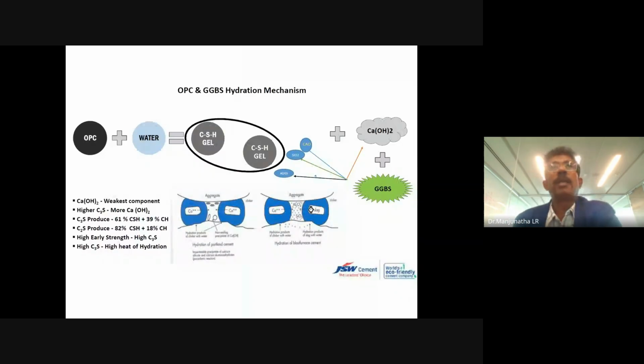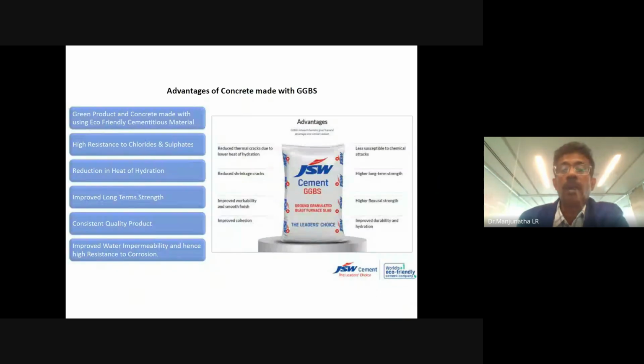The advantages are many. GGBS as a product is resistant to sulfates and chlorides, and has reduced heat of hydration, especially for raft foundations. When you're designing a building with a 2.5 meter, 3 meter, or 4 meter raft, you are going to have a very good concrete with a temperature gradient of less than 20 degrees centigrade, because temperature gradient is very important when you are designing a raft foundation. So GGBS plays a very important role.